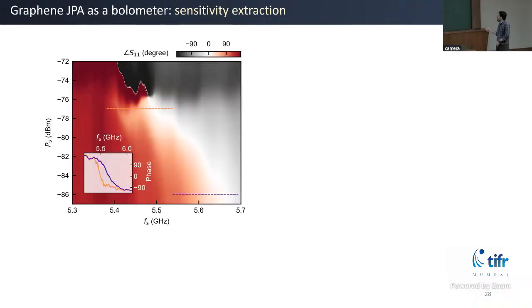Now, another very interesting knob in our device is this non-linearity. It turns out that when you drive the device from linear to non-linear, the resonance linewidth actually decreases, so it becomes very sensitive. I'm showing you here two line traces of the resonance curve. One is at low power, and this is at high power, close to the critical point. You can see that when you drive it non-linear, the resonance becomes very sharp.